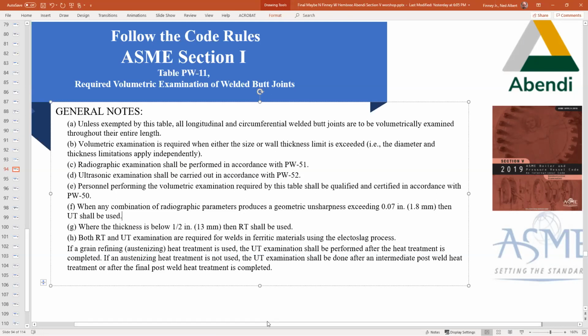This is an exception. Again, the code does make exceptions to the methodology that we use. Where the thickness is below 1/2 an inch, then radiography shall be used. H, both RT and UT examination are required for welds in ferritic materials using the electroslag welding process. If a grain refining austenitizing heat treatment is used, the UT examination shall be performed after the heat treatment is completed. Again, telling you when.